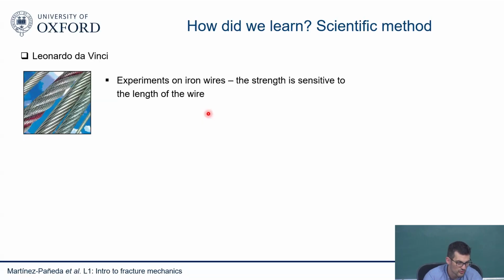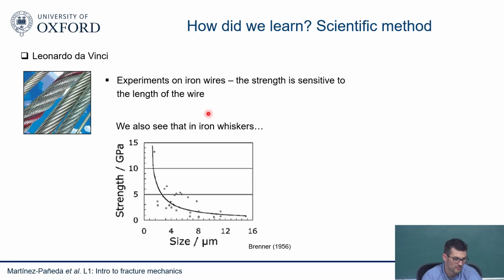And this is something that you see, for example, if you do tests on iron whiskers. If you plot the strength versus the size, you can see that there's a very strong sensitivity of the strength of the material to the size. Eventually, if our piece of iron is big enough, then we get to some sort of plateau where we have enough distribution of defects, so we're basically in the same spot. So that's what we normally call the strength of our materials.